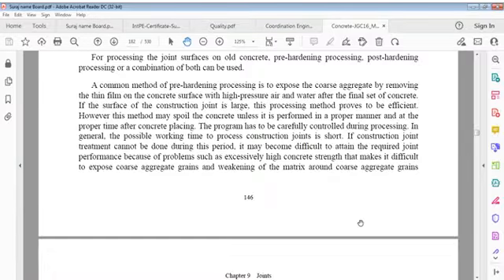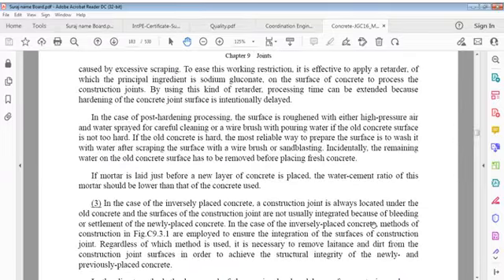If the surface of the construction joint is large, this processing method proves to be efficient. However, this method may spoil concrete unless it is performed in a proper manner and at proper time after concrete placement. It has to be carefully controlled. In general, the possible working time to process a construction joint is short. If treatment cannot be done during this period, it may become difficult to attain required joint performance because of problems such as excessively high concrete strength that makes it difficult to expose coarse aggregate grains, and weakening of matrix around coarse aggregate grains caused by excessive scraping.